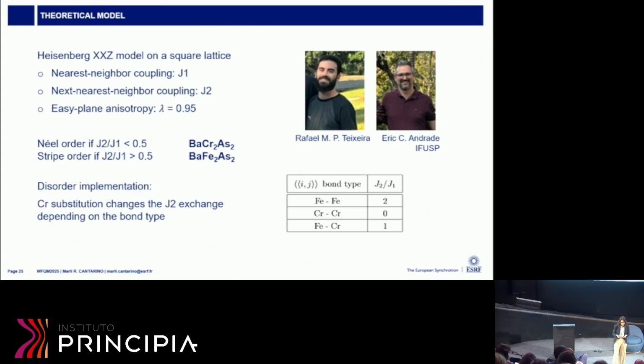In the case of an iron-iron coupling, J2 will be 2, especially because in RIXS we only probe the iron contribution. If I have chromium-chromium, I don't see it. If I have iron-chromium, I see half of the exchange parameter.